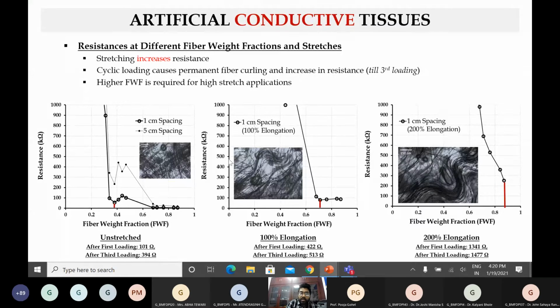If we have 100% elongation, once we release the elongation, there is some microscopic undulation which happens within this, which is called fiber agglomeration. Basically, the fiber comes out of the matrix due to this huge pull, like a material mismatch. Now this material is no more as conductive as it used to be when it was subjected to 0% elongation. So what really happens when we have 100% elongation? How much volume fraction do we need? Using optimization, we found this value to be close to 0.7, which is fairly high in terms of fibers.